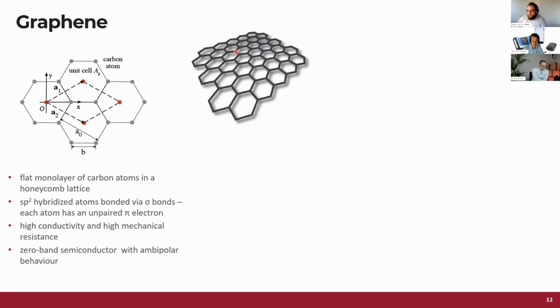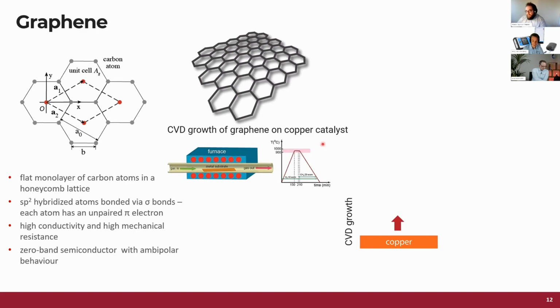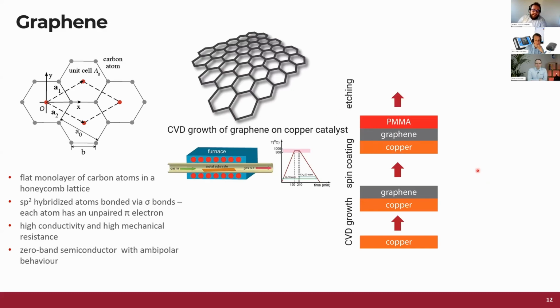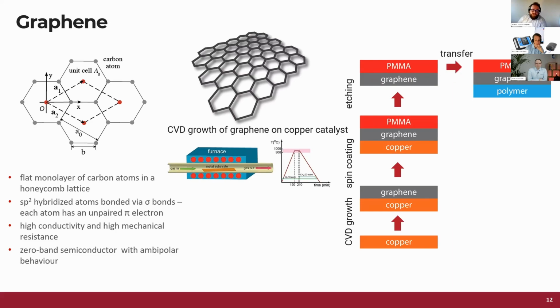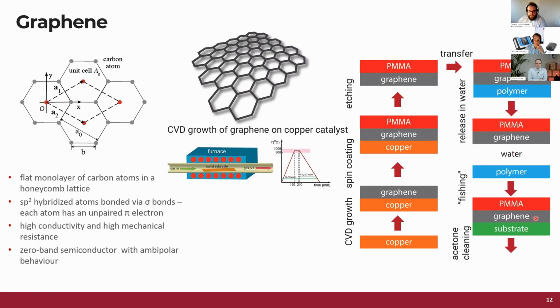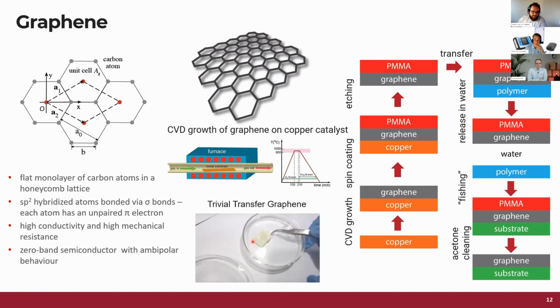How it's prepared is that we grow graphene on copper foil with a CVD process in a furnace at very high temperature, feeding the furnace with some carbon source. The carbon reacts with the copper, which is the catalyst, and forms a monolayer of graphene on the surface. Then we can spin coat it to protect the graphene, etch away the copper, and transfer it to, for example, a polymer. I personally buy these so-called Trivial Transfer Graphene pieces, which are actually transferred pieces of graphene covered with PMMA on a hydrogel, and upon addition of water they release, and you can easily cut them and fish them onto your substrate of choice.